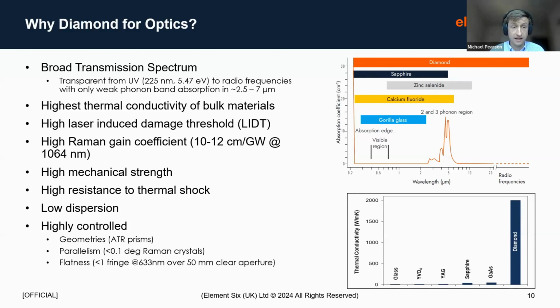I've just talked a bit about LIDT, so laser induced damage threshold. The diamond substrate itself typically has a very high laser induced damage threshold. The limitation is often the coatings, which I'll talk a little bit about in the challenges later on.